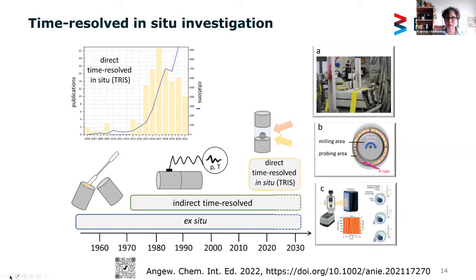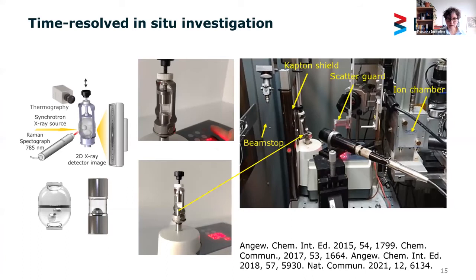Okay, and this is our in situ system and our setup we used. You can see we have had this Easter egg in the beginning. We made a bit of an improvement when it comes to the reactor. And so this has to be transparent so that we can shine our Raman laser in, so we know something about what's happening on a molecular level. We also use thermography to get information about what's happening temperature-wise. And we use, of course, X-ray diffraction for long-range order.